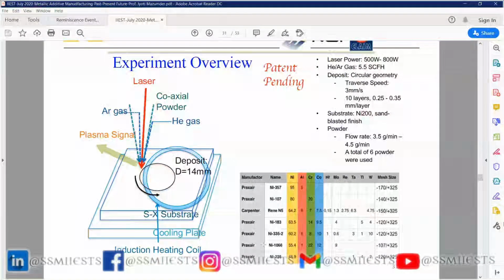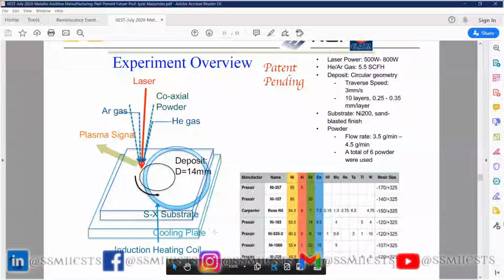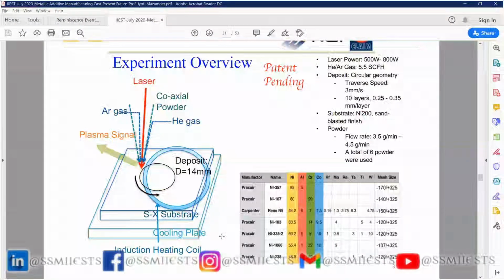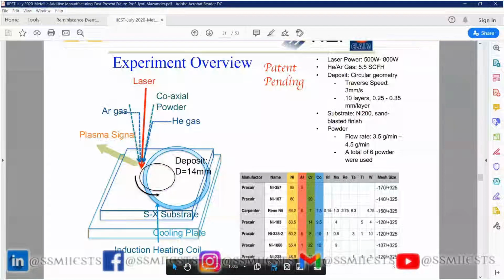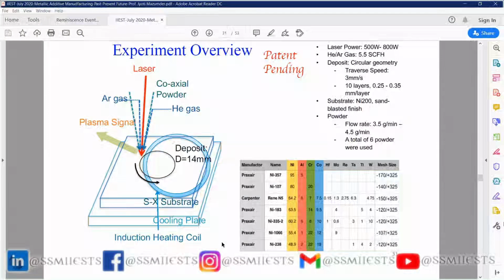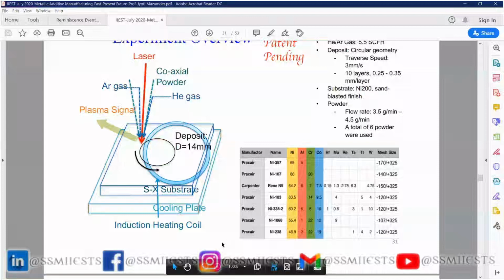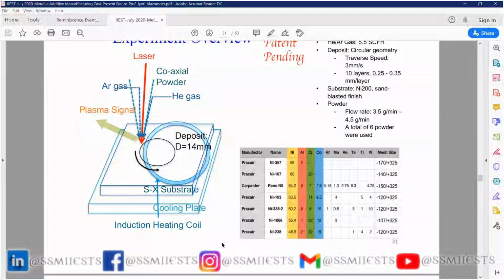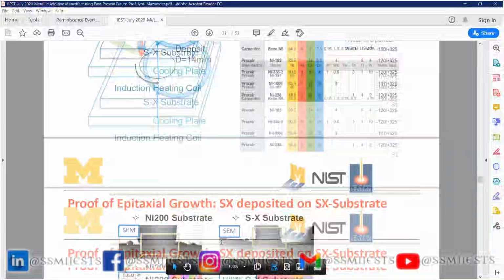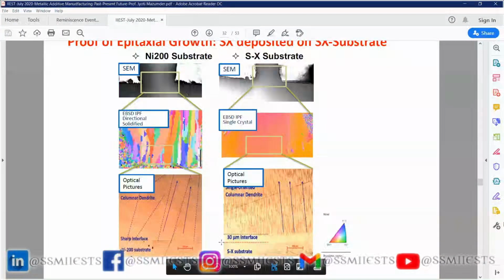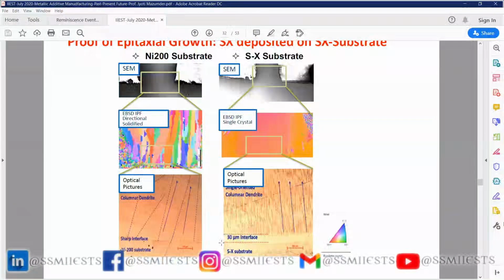Once we did that, we tried all kinds of different alloys, from Praxair and others, and we found that yes, I can control it effectively for almost any alloy. There's another trick which I haven't told you: if I'm going to make a single crystal, I have to start with a single crystal. You need the seed. If I don't start with a single crystal, when you deposit and look at the EBSD, I'm getting all kinds of different grains going in different directions. Whereas if I start with a single crystal, EBSD tells you that if I maintain the temperature gradient carefully, I'm also growing a single crystal.